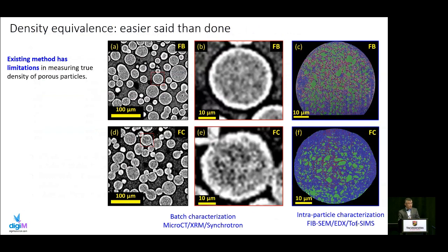So how do we exactly measure the true density? The density measurement on these microparticles, microspheres with porosity, with sub-resolution API, small particle size dispersion, is not easy. With simple measurements such as volume weight, it's difficult to get accurate volume measurement when you have a macroporous material. To further complicate the approach, if we take images, we might assume they have the same intensity, which would allow us to convert that into density. That's also not very straightforward.